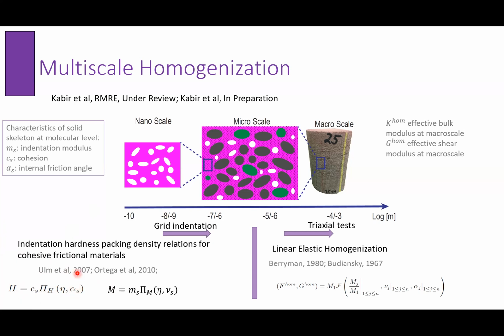I assume the friction, because to have the friction, I would have to do indentation with two different probes, with two different angles. So I assume the friction coefficient, but at least I have the cohesion at the lower length scale. And to be able to go upward, what I showed upward, I'm looking just at elasticity, but I have another presentation where we use poromechanics to look at the failure surface. I didn't present it here, but we look at the failure surface macroscopically, because if you have the different phases, and for each phase you have the value of C and alpha and M, then you can look at the macroscopic level what is going to be the failure surface of the composite, but I did not present it here.